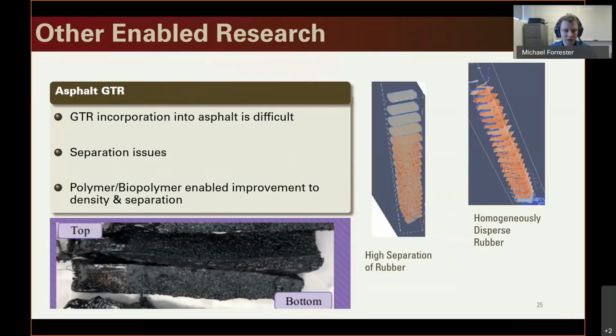The last thing I wanted to mention before we wrap up is some of our work on our asphalt GTR. So GTR is used to modify asphalt in a similar way that polymer can be used to modify asphalt. The one challenge is that there are some big separation issues that can occur over time. And that causes some pretty serious performance disadvantages in the field. And so one of the things that we had originally thought of was, can you fix the separation issue by basically combining the GTR with some other rubber particles to decrease the density so that they don't settle.